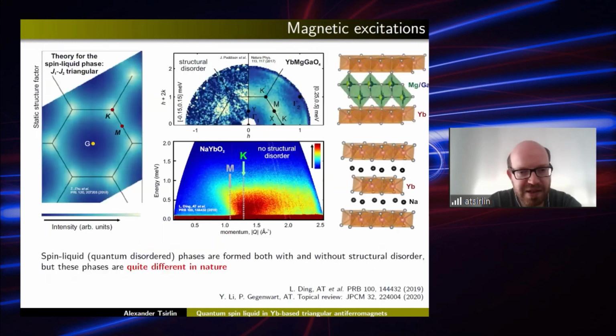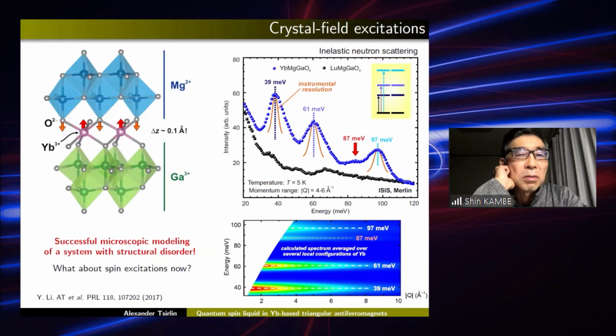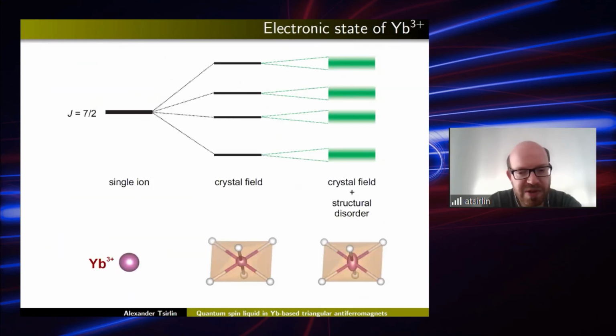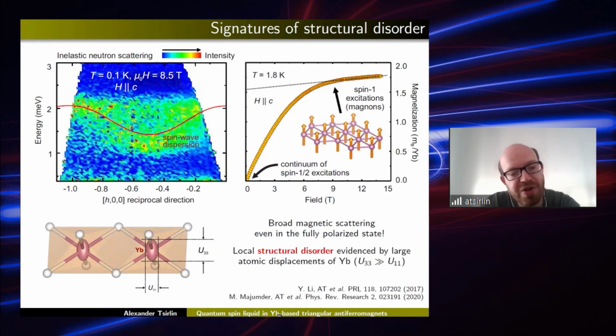You talk about the disorder, but this disorder, is it dynamic disorder or static? In this case, it is static disorder. Yes, this is the static disorder, at least that's how we understand it. Because if you measure XRD down to low temperatures, you will see that the displacement ellipsoid remains anisotropic. Even at low temperatures, even at 100 Kelvin, it's very much elongated.